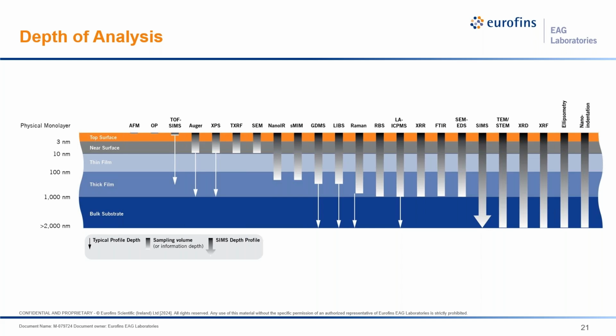These surface analysis techniques are up to 3 orders shallower than other common and routinely used analytical techniques, such as FTIR or SEM-EDS. This means that surface contaminants or foreign elements in very thin films can be detected on samples by time-of-flight SIMS, XPS, or Auger, but most likely will be missed by other analytical techniques. The arrows indicate that deeper depths are available in some techniques by depth profiling modes or depth distribution analysis.